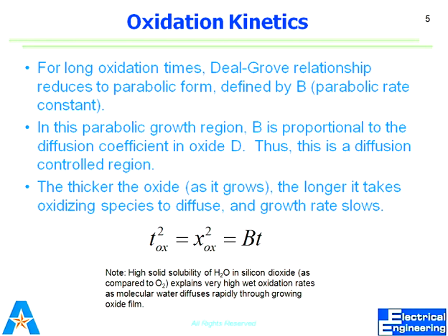So that's why we say that when the thickness of the oxide becomes very thick, at that time the reaction rate would get slow due to the diffusion, because it's limited by the diffusion. So we say this is diffusion controlled region. It was reaction rate controlled region, and this is diffusion controlled region. Any question up to here?